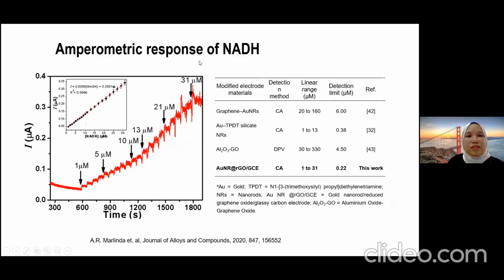Okay, so for the amperometric response, we introduce 1 micromolar of NADH, right, and then up to 31 micromolar. So from the linear graph, we can calculate the limit of detection to be 0.22 micromolar. So it shows the lowest detection limit as compared to previous studies using graphene or graphene-based nanocomposite. So our study shows the lowest limit of detection.